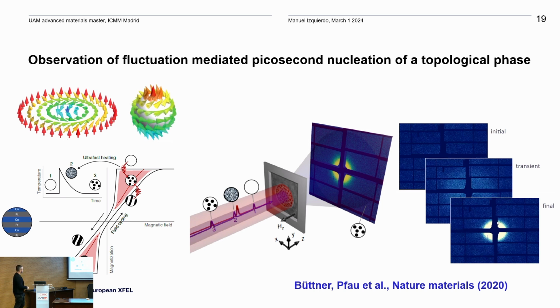The way they did this is they shoot the sample with 3 pulses, and they measure with the FEL how the system evolved as a function of time. The first pulse either switches back to the initial state, and this will give you this image. Then the second pulse will give you this intermediate state, and with the third pulse you do the nucleation. You can see how the scattering patterns in the DSSC detector change as a function of the 3 different states.